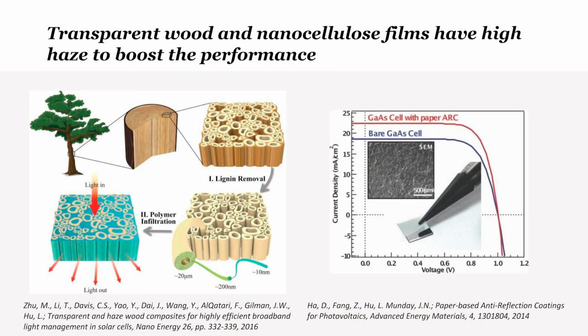So when we would prepare transparent paper or transparent wood, let's take the transparent wood, we would first remove the lignin. So if you take a wood wafer, the brown parts in the wood come from the lignin. And when we have removed the lignin, we can infiltrate the remaining wafer with a polymer, resulting in a transparent material. The added benefit from utilizing transparent wood is that it scatters light in the forward direction. This in practice means that the light will travel a longer path inside the solar cell, which increases the light harvesting in the actual device.